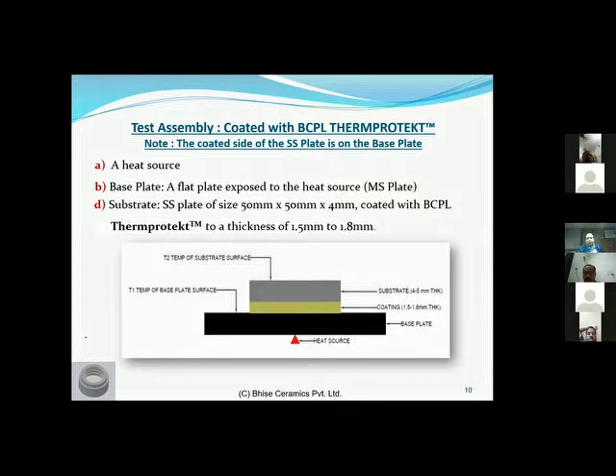So now what we did was, both the assemblies, we started heating up with the same amount of heat, kept the heating in the same way, and took the measurements for 50 minutes and 70 minutes to see how the hot phase temperature and how the cold phase temperature vary. And then we did a typical time versus temperature graph. Now, how does that look?